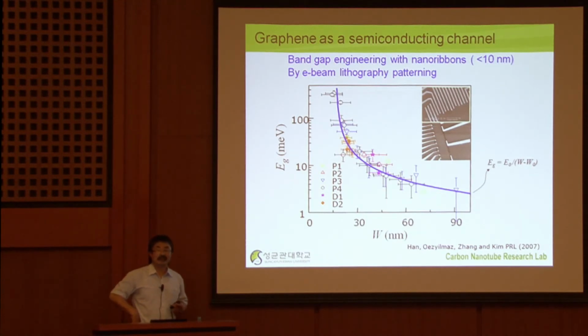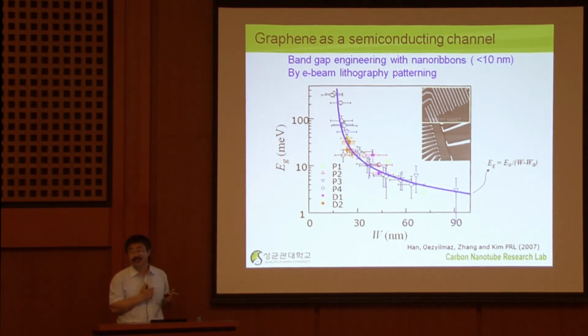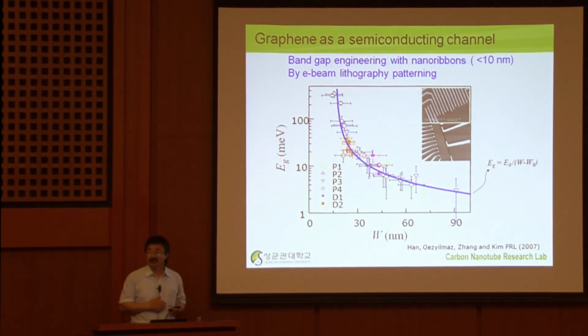Now, a typical single carbon nanotube, which has a diameter of 1.4 nanometer, has a band gap of 0.7 electron volt. We still believe this is too low compared to silicon. Silicon has an energy band gap of 1.1 electron volt, which is fairly enough to operate at room temperature. But with 100 milli electron volt, there's no way to use this as a transistor. That means you have to go further, less than 10 nanometer. Okay, 5 nanometer, yes, we can have a reasonable energy gap. The question is, can you do that?